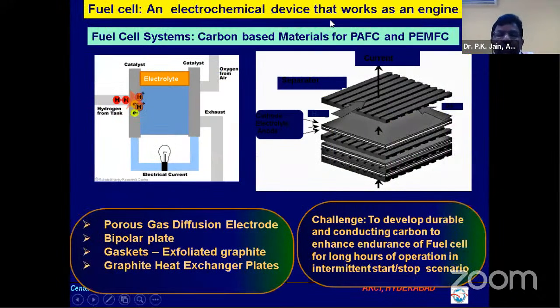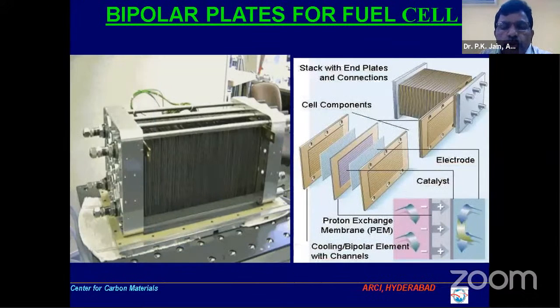This is another application, a bipolar plate for fuel cells. These are field flow channels where on one side hydrogen is flowing and on the other side oxygen is flowing, and that's how we get the fuel cell. This is a stack of bipolar plates in a fuel cell, and then this is a multiple stack of many bipolar plates, because each single cell cannot give you the voltage required, only 0.7 volt. So for a 1 kilowatt or 10 kilowatt fuel cell, you require a stack of bipolar plates. The major cost of the fuel cell comes from the bipolar plate, and the cost of the bipolar plate comes mainly from the processing. So we have developed it from exfoliated graphite, which has reduced the cost very drastically.